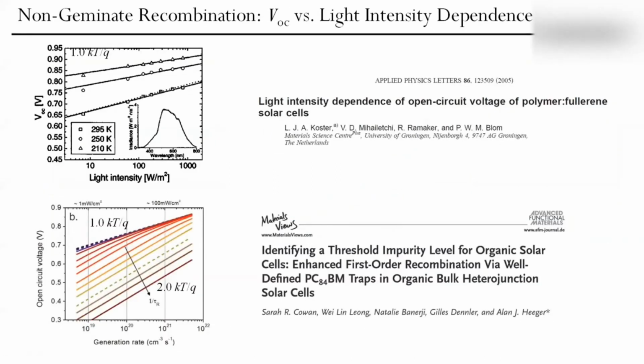Then the next step is to address non-geminate recombination, because once we have already described generation of excitons and geminate recombination, we already know how many free charge carriers are created in our active layer. However, in order to proceed further, we need to understand how many of these free charge carriers we will lose in the active layer of our solar cell while we try to extract them and collect them at external electrodes. So one of the very simple techniques to address this question, at least qualitatively, is to measure VOC, open circuit voltage, as a function of light intensity.